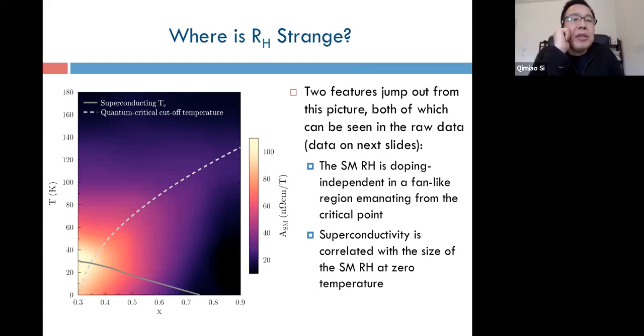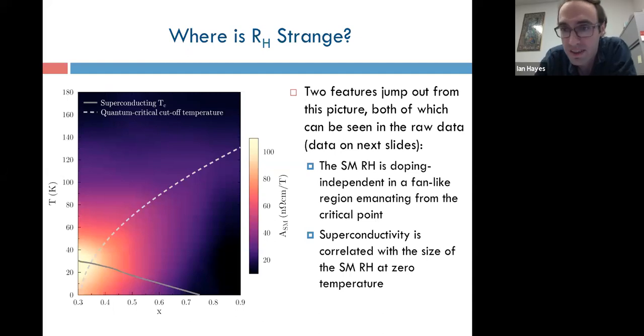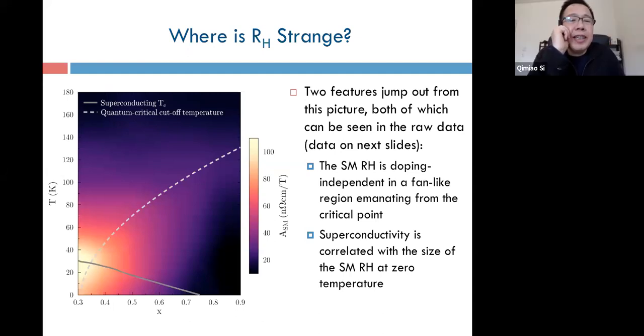Ian, do you mind if I interrupt you? Yeah, not at all. If I take the dashed line literally, it's somehow in deviation with my understanding of what happens in the phosphorus doped materials. In other words, the critical slowing down doesn't actually go all the way to zero, that even at around optimal doping, there seem to be various indications that there's some truncation. So the dashed line, in that sense, I would have thought doesn't really terminate at zero.